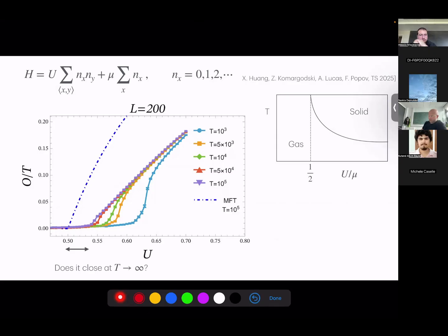It seems that this large k expansion indicates that the phase diagram looks something like this. In other words, as you increase temperature, you may end up in a solid phase as long as U over mu is larger than or equal to 1/2. But this point here may be a little bit smaller than 1/2. Could be a little bit larger than 1/2 as well. So that's at least what we have found so far. Are there any questions at this point about this model?